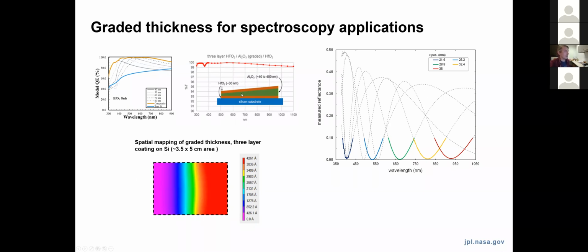And so we've fabricated a coating like this. This is a measured spatial map of the change in aluminum oxide thickness in this case that's sandwiched between 2 uniform layers of hafnium oxide, and some of the measured spectra at different points along this device as you step across, showing indeed that we're getting less than 1% reflectance across this wavelength range.